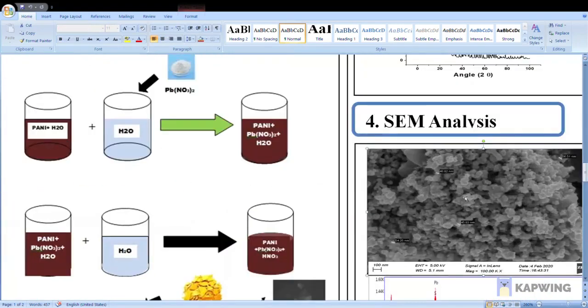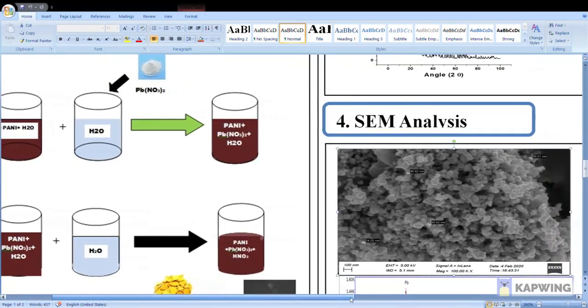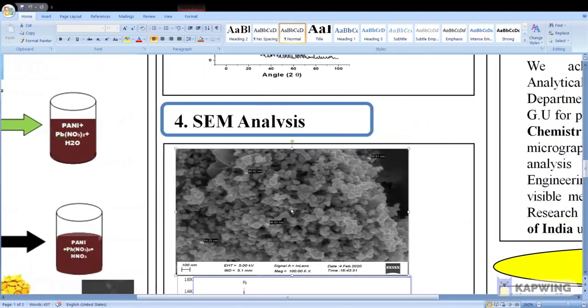SEM analysis, you can see that the particles whose diameter are ranging from 45 nanometer to 57 nanometer can be observed. From EDS, it is confirmed that in lead sulfide nanoparticles, the high presence of lead and sulfur is there, including nitrogen, oxygen, sodium and carbon.